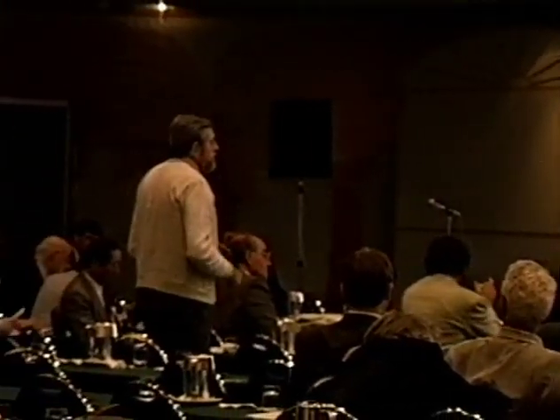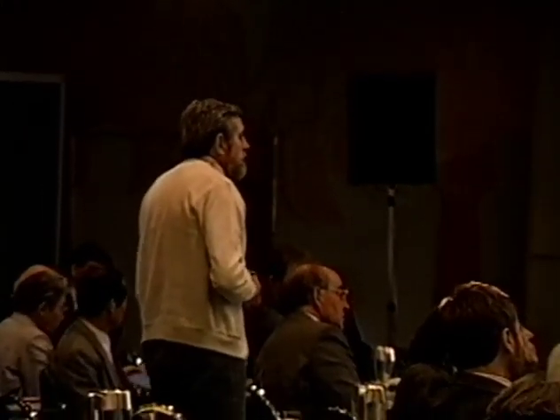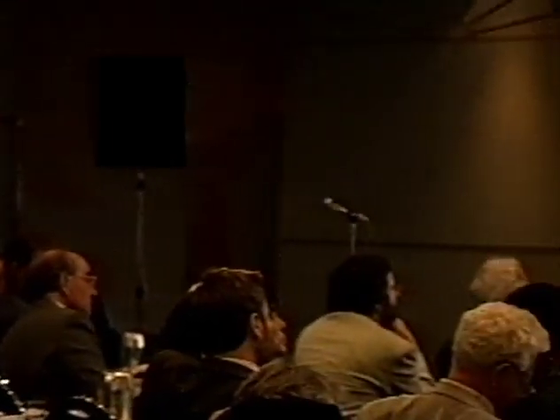What did you mean when you said 0% vacancies? Vacancies less than 10%. If you assume that the system is pure without vacancies, you get a good fit of the results. And if you assume some random vacancies, small vacancies, you can also get a good result. Vacancy is what, though? Empty sites, yeah? Empty interstitial.